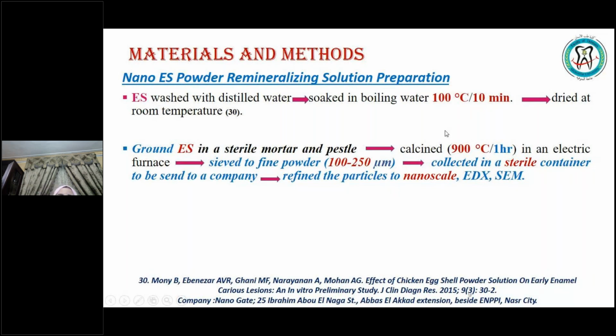And after drying to room temperature again, those eggshells were ground in a sterile mortar and pestle. They were again calcined to 900 degrees centigrade for 1 hour in an electric furnace. Then they were sieved to a fine powder in the micro size again, which was 100 to 250 micro size.